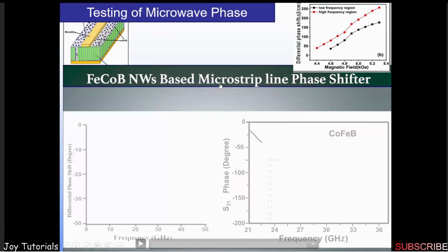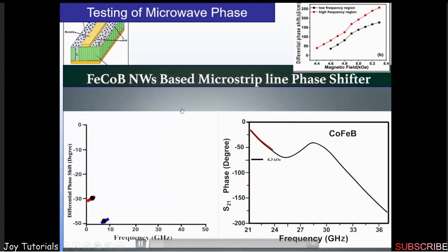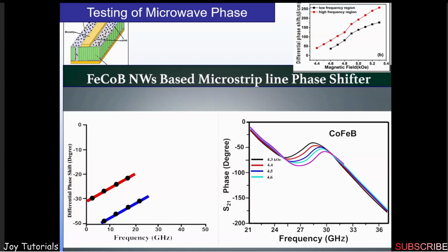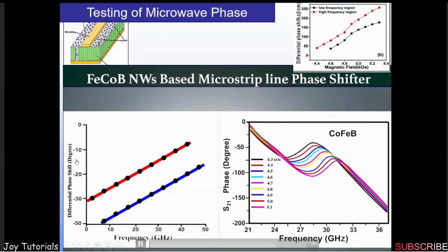Then I'll show you a nanowire-based line phase shifter, designed from the same transmission line which we designed for a filter, and we are using the differential phase shift, because we can measure the phase shift, the real and the imaginary part, through the network analyzer. Just using the real part, we can define the filter, but using the imaginary part, the phase shift, we can have a differential phase shift with respect to the phase shift we got at zero field. As you can see here, at different frequencies, we have differential phase shift. Here the phase shift is huge, but it is of no use, because at this frequency there is a huge insertion loss because of the stop band action.